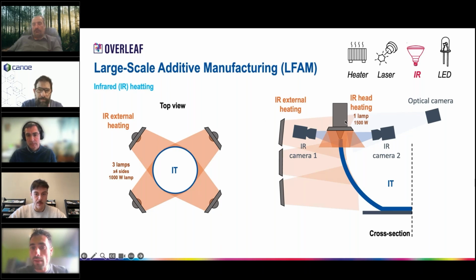Besides, we have an IR lamp in the printhead. This allows us to increase the temperature of the top surface, and in this way increase the adhesion between layers, making the whole structure less anisotropic.